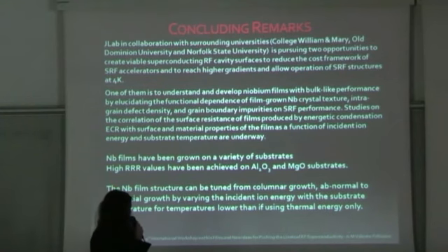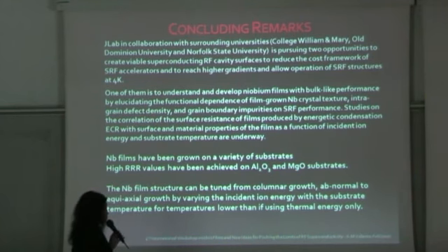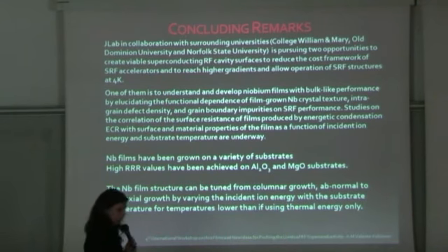We have been able to achieve high triple R values, and we have some evidence that we can tune the structure of the film by playing with the bias energy, the bias voltage, as well as the temperature, which would allow us, for example, to achieve the same results that we would achieve with temperatures that are much higher if we were only dealing with thermal energy.